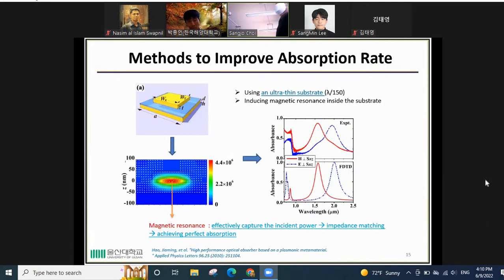And also to improve the absorption rate of the antenna, normally people use ultra thin substrates at around lambda over 150 nanometer. This structure can induce a magnetic resonance inside the substrate, so that this magnetic resonance can effectively capture the incident power, and then achieve perfect absorption because of the impedance matching with the surrounding medium.